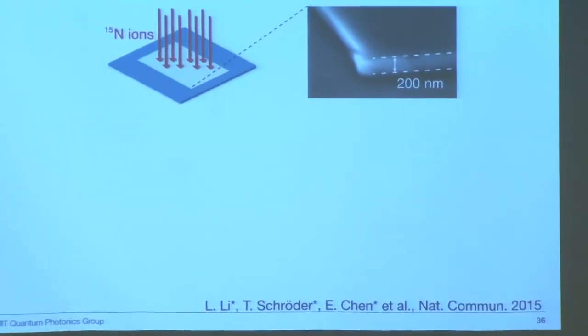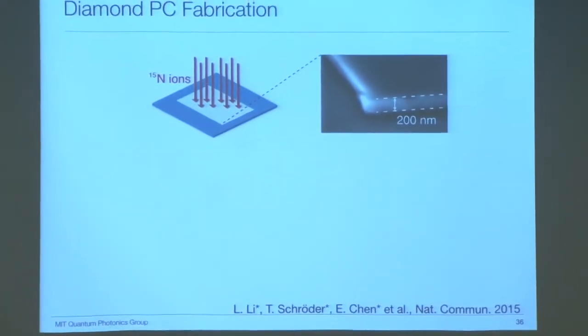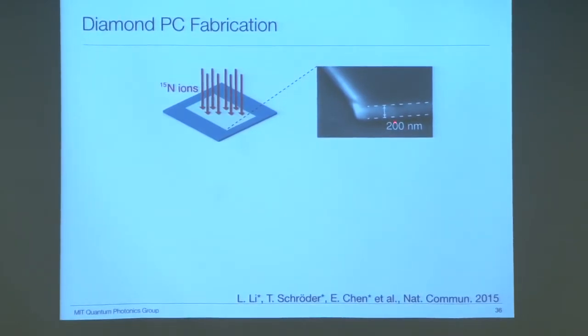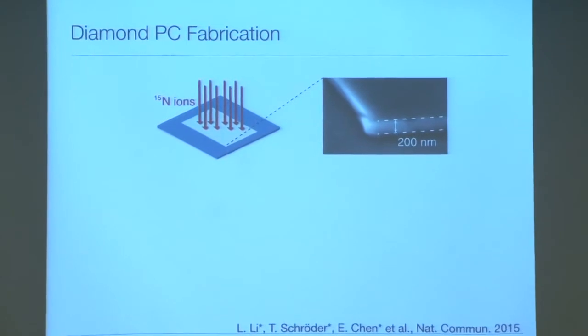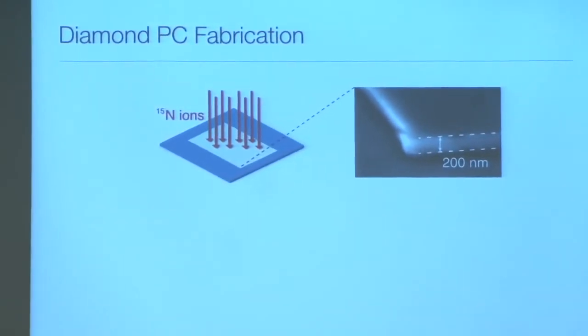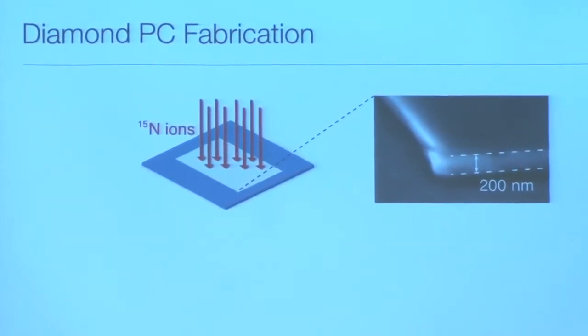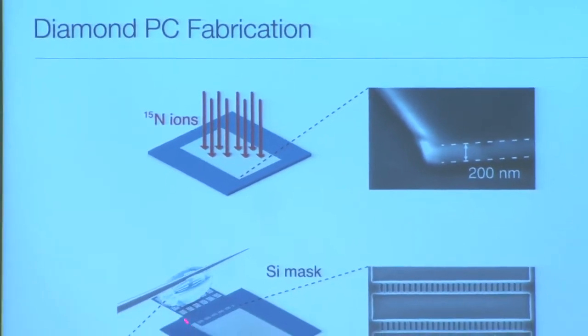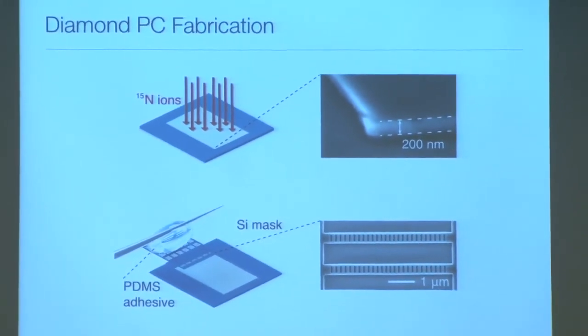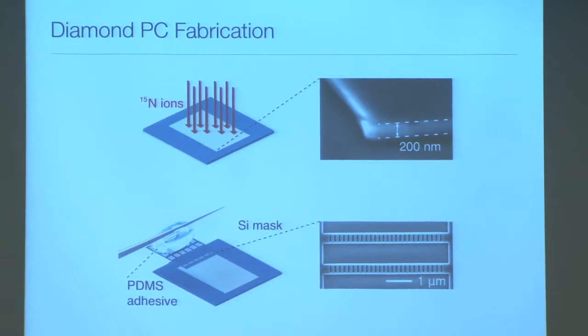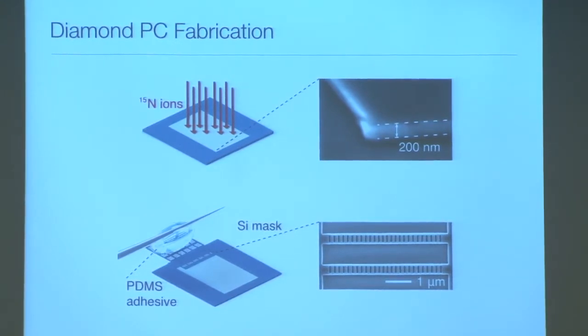The fabrication begins by thinning a 5-micron diamond membrane to 200 nanometers, and then we implant nitrogen vacancy centers by nitrogen ion implantation and annealing steps. Then we transfer the silicon mask onto the diamond membrane. This is an SEM image of the silicon mask on top of the diamond membrane.